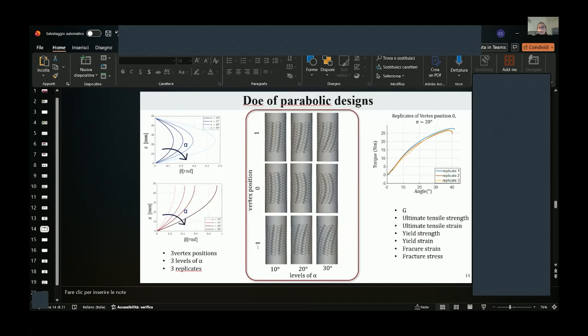Similarly, for the parabolic designs, we imposed 3 vertex positions, so in the middle of the specimen, upper and bottom part. Again, 3 levels of alpha, 10, 20, and 30 degrees, and 3 replicates per each condition. And again, we extrapolated the most important factors after performing pure torsion tests. So let's see the most relevant results.